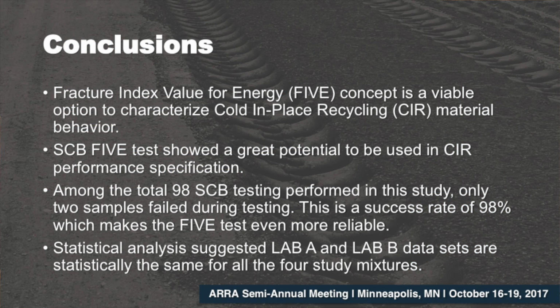So one of the conclusions would be that the fracture index value for energy of the SCB test is a fracture energy test that is viable to optimize the cold-in-place recycling process, to be able to look at those materials and distinguish between them. It also showed great potential to be used as a performance specification using the SCB, which is the most practical test that could then be translated into quality control, quality assurance. Among the 98 SCB testing specimens performed in this study, only 2 of the samples failed during the testing itself. This is a success rate of 98%, which makes that SCB test even more reliable.